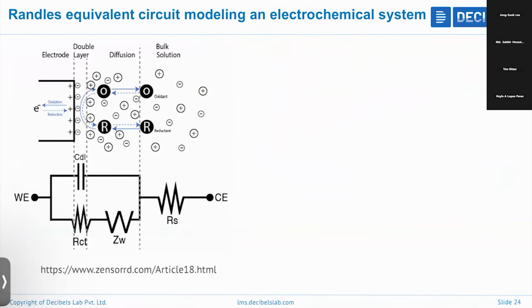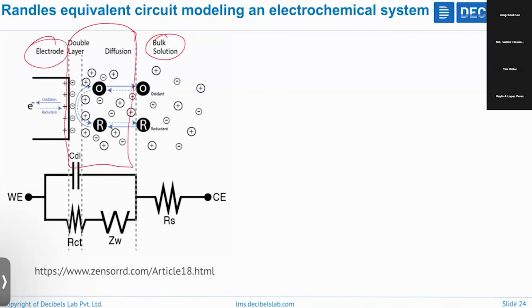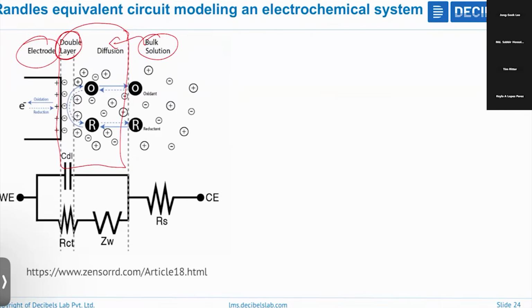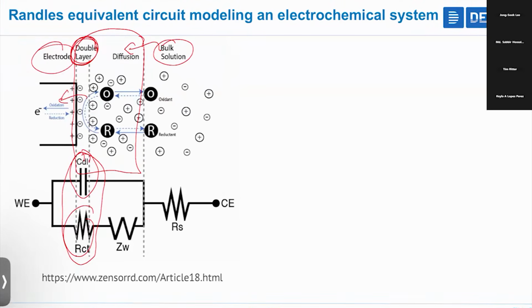So let us understand the Warburg and CPE in the real system. So if you consider a real electrochemical system, okay, this is an electrode and we have a bulk solution and this is the interface, right? This is the interface near that electrode, and the ions have to move from the bulk solution and diffuse through this, and there is a formation of an electrical double layer, and then it should enter into the electrode. Okay, so the resistance corresponding to this double layer and this one is actually RCT, the charge transfer and double layer, corresponding to this region of the battery.